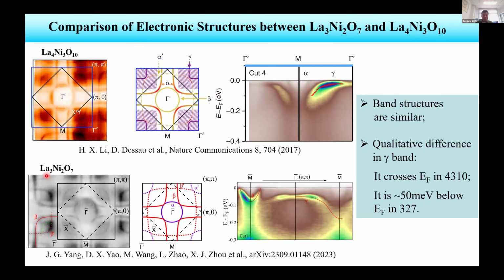Then when it comes to the 327 system, as we measured here, this is the Fermi mapping. This is the obtained Fermi surface. We have the alpha Fermi surface and beta Fermi surface, but here we don't see the gamma Fermi surface, because in this case the gamma band is 50 meV below the Fermi level. So if you compare the 327 system to the 4310 system, mainly the band structures look similar, alpha, beta, and gamma, but the major qualitative difference lies in the gamma band.